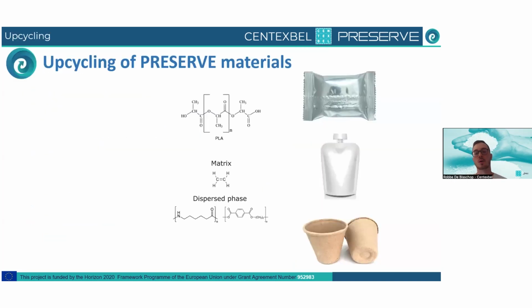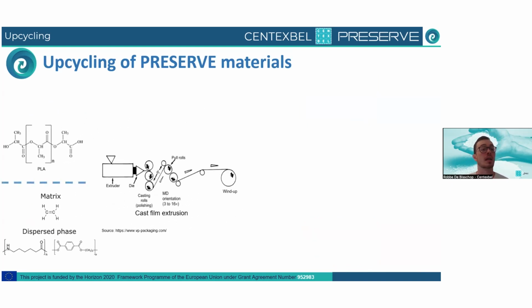So first of all, a highlight of the activity, both of the technologies, to situate them into the project and also in which materials we have. Here you can see the three demonstrators, the food demonstrators on the right. These materials are, on the one hand, PLA based, and on the other hand, multi-layer materials from polyethylene and also PET or polyamide to get the barrier properties. We will be using these materials to form, on the one hand, with the PLA, the self-reinforced materials. And on the other hand, with the multi-layer materials, we use the microfibrillated materials, with polyethylene being the matrix, and then using this PET or PA material that is very strong as a fibrillated dispersed phase inside of this polyethylene.